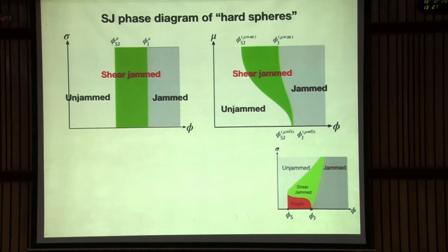Okay, Ganesh, have a question back? Okay, so towards the end, you commented on soft spheres. If there is an inherent scale for the stress, what is the phase diagram like? Okay. This is one case, this is a simulation result of critical load model we call. This means, to activate tangential force, I set a force scale. So if normal force is less than certain value, they behave as frictionless particle. And if pushing force is larger than one constant value, one, then it behave like frictional particle. And this way, we can, one, okay, this is just scale of, non-dimensional scale of stress. But anyway, one single force scale is important to make this curved boundary.